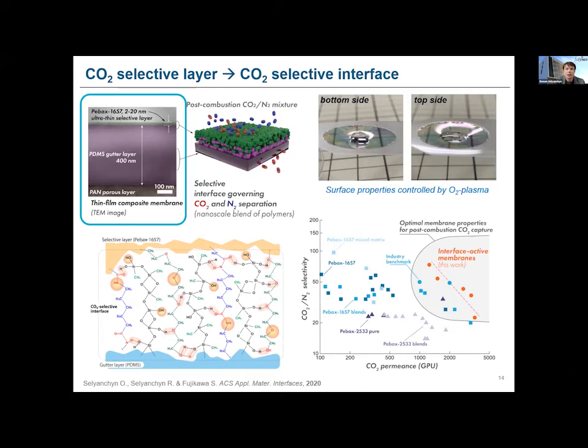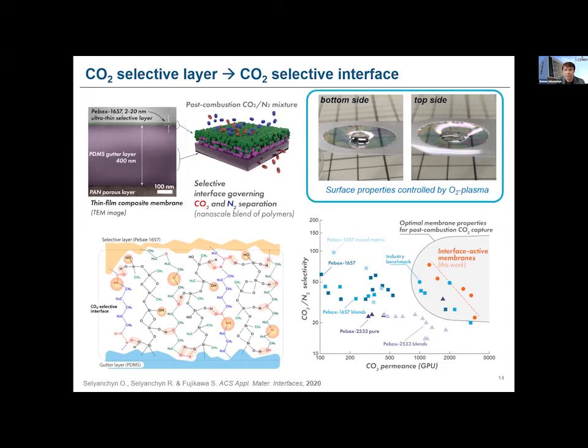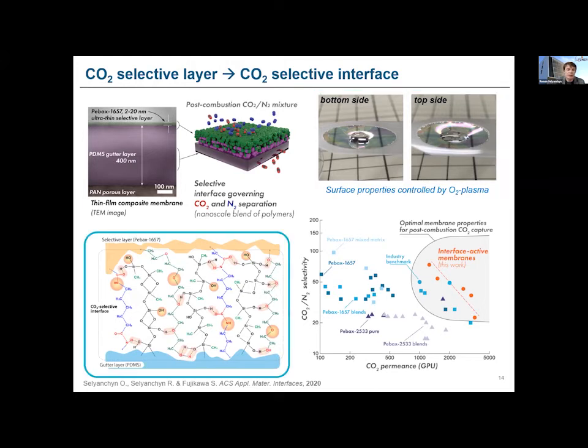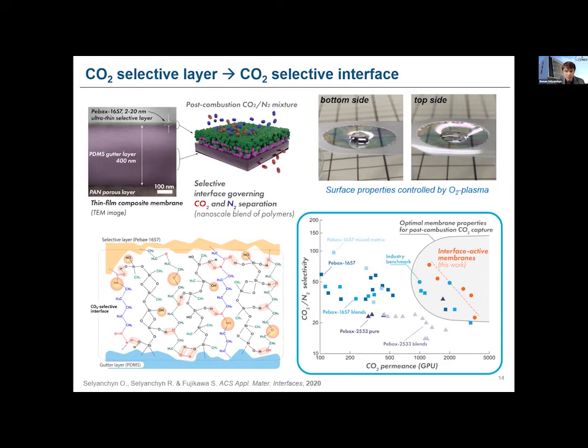And in addition to thinning, we have also changed the activity of the interface formed between 2 layers, which is manifested by the surface properties. For example, here, as you can see, is the water contact angle measurement on the 2 different sides of the membrane. And we have elucidated that this ultra-thin selective layer composed of the selective copolymer is intermixed with the plasma-treated polydimethylsiloxane and forms a selective barrier with very remarkable gas separation properties, as shown in this final image, where these red points indicate our work. And as you can see, they all fall into the optimal membrane properties for post-combustion CO2 capture.